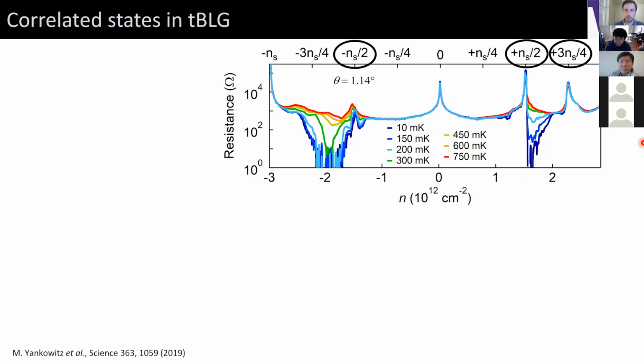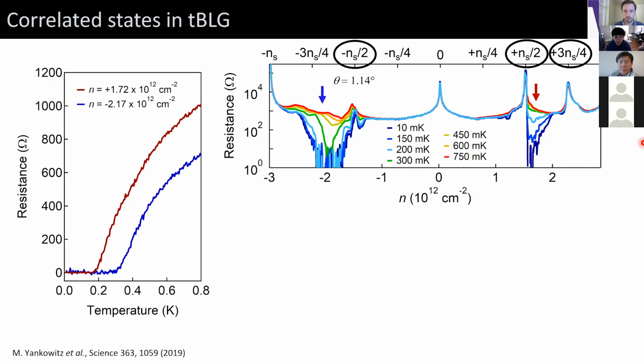Now, if we go slightly away from the commensurate quarter fillings and measure the resistance as a function of temperature, we see that it actually quickly drops to our noise floor, basically immeasurably small at low temperature. And this is indicative of the emergence of superconductivity in the system.